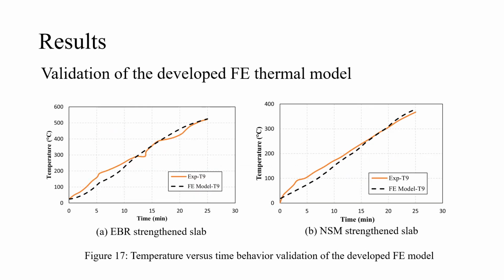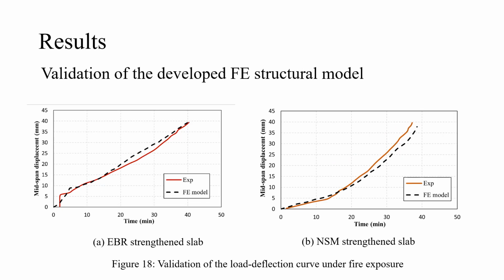Nodal temperatures were obtained from the heat transfer analysis performed in the thermal model, and they were validated with the experimental temperature profiles. Finally, the load-deflection curve of the two strengthened slabs under fire exposure was obtained from the structural model. As can be seen, the finite element model can perfectly predict the displacement behavior of the slabs when exposed to fire.